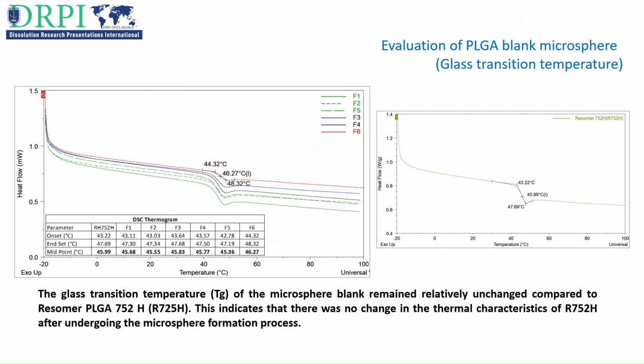These are the differential scanning calorimetry results, which showed similar onset values for all formulations and pure PLGA. The glass transition temperature of blank microspheres remained unchanged compared to pure PLGA, indicating that there is no change in the thermal characteristics of PLGA after microsphere formation.